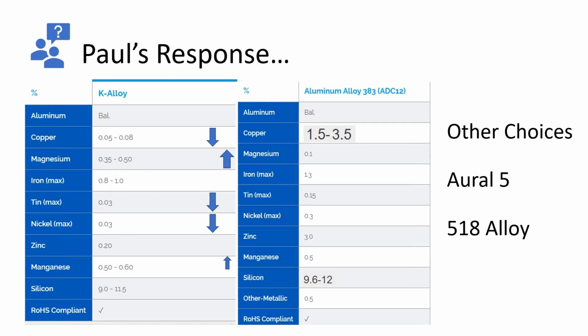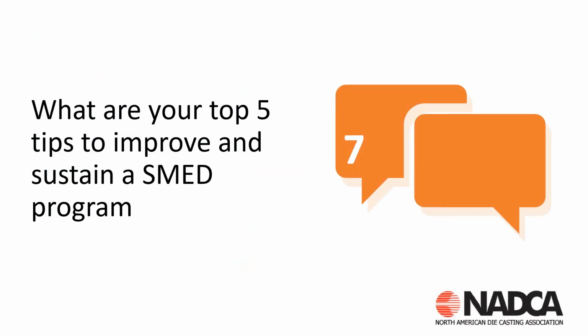Summing that up, mechanicals, virtually the same, a little bit higher elongation for K alloy. The chemistry, definitely the copper change as a low level of 0.05 to 0.08 on the K alloy does lead to better corrosion resistance. Moving on to the next question.